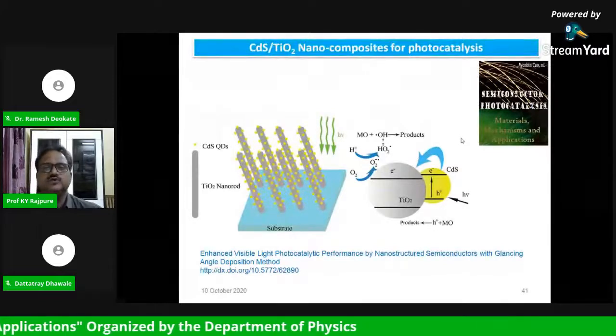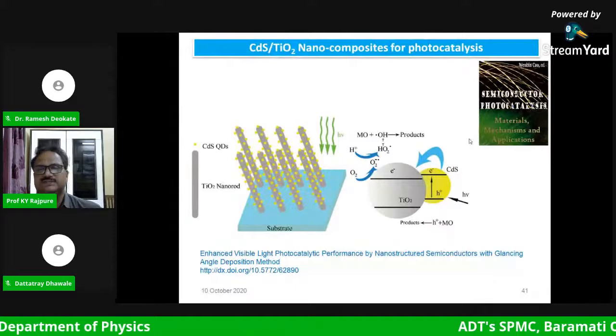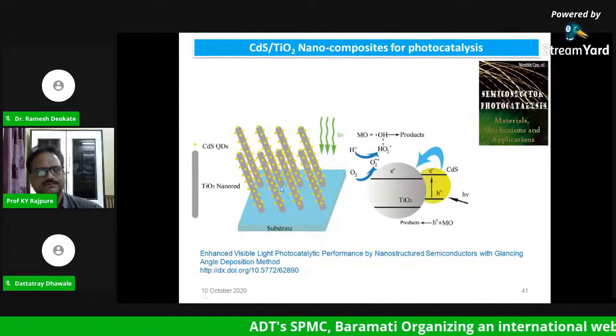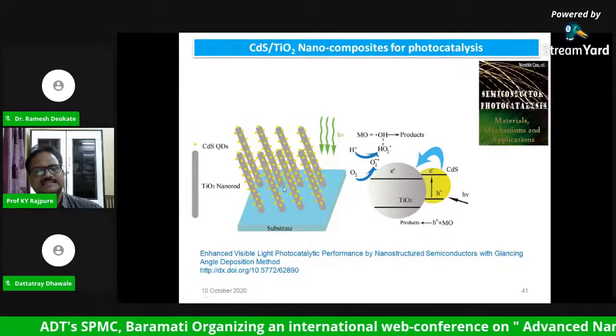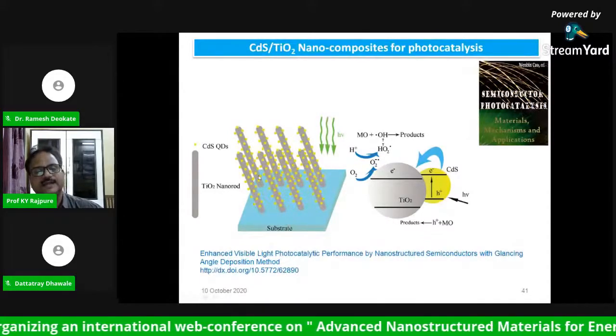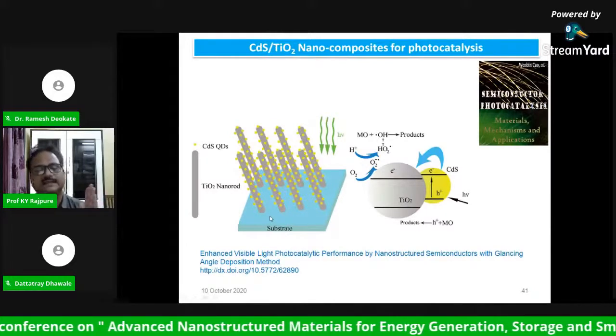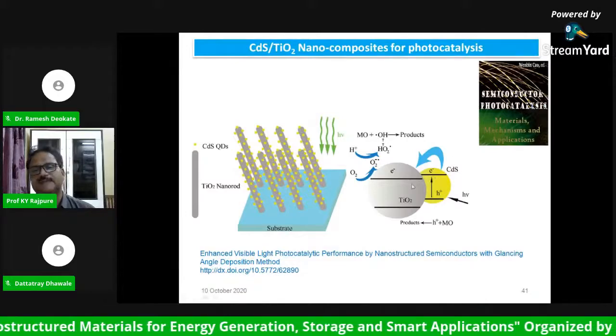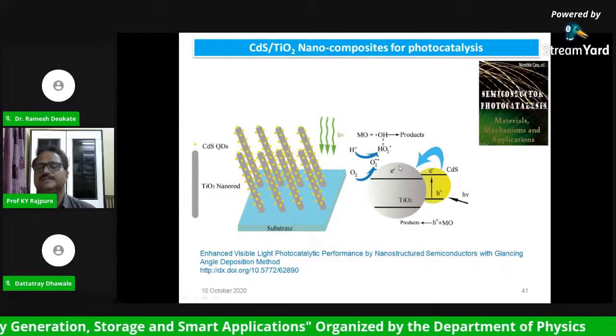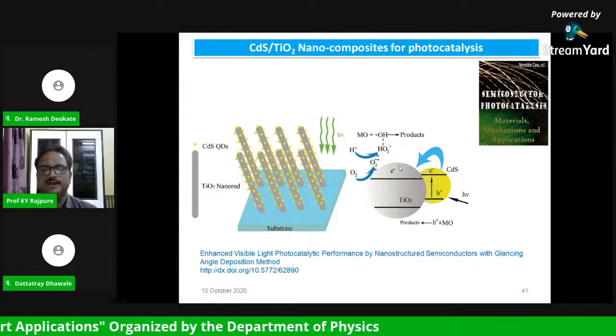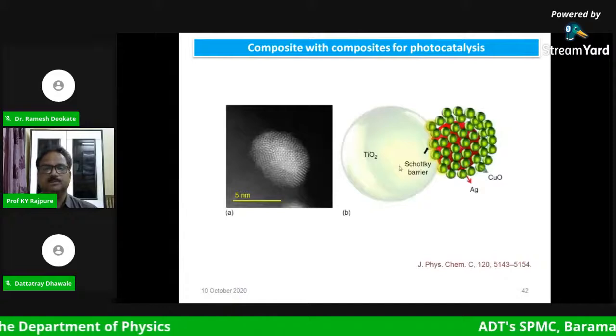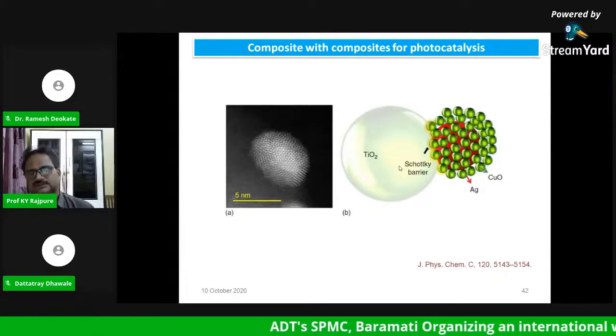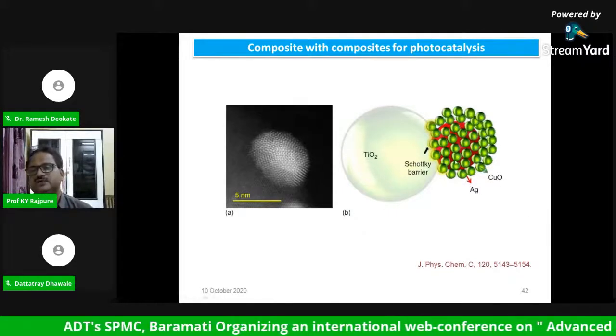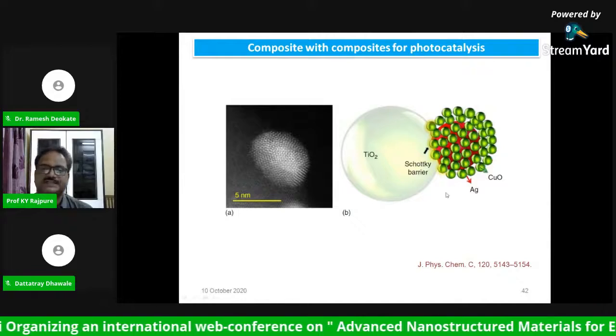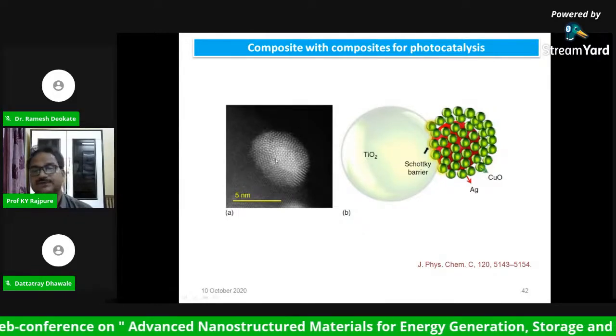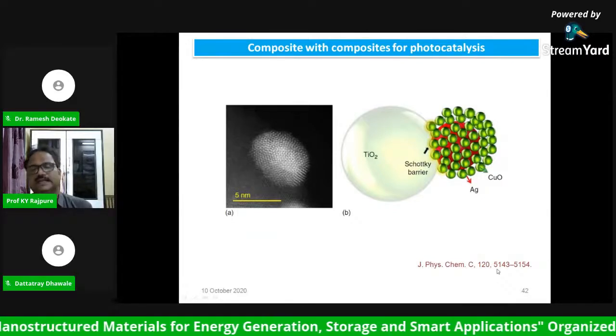Here, the example of a cadmium sulfide TiO2 nanocomposite for photocatalysis is schematically shown, where cadmium sulfide quantum dots sensitize TiO2 nanorods. And these TiO2 nanorods are grown vertically upward from the substrate surface. So this is the band position, and it is possible to improve the photocatalytic efficiency. The main aim is to avoid the recombination of electron and hole. People are making composites between composites. So this is Ag doped CuO, and this is the corresponding TEM image of the composite of Ag doped CuO with TiO2. People have also reported higher photocatalytic efficiency.